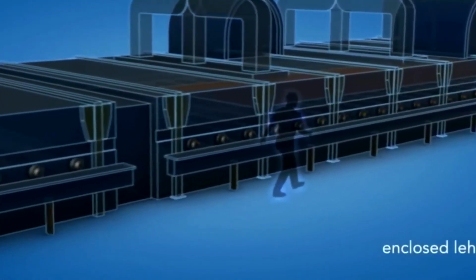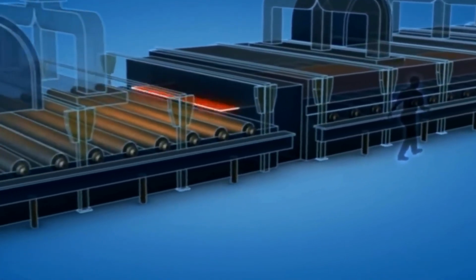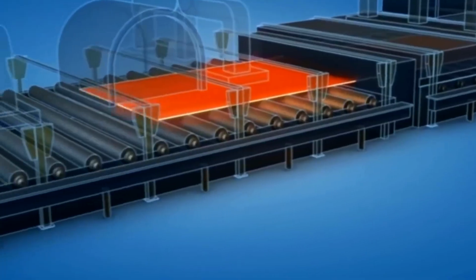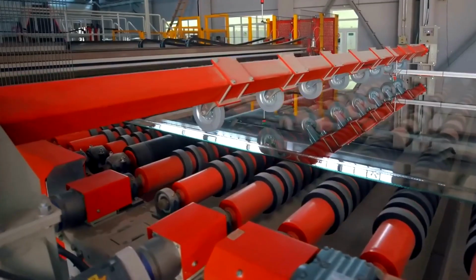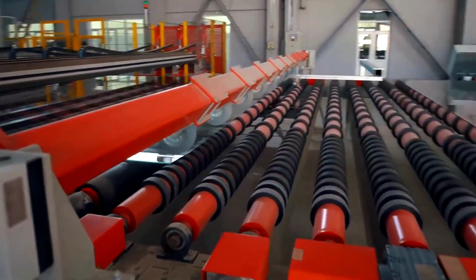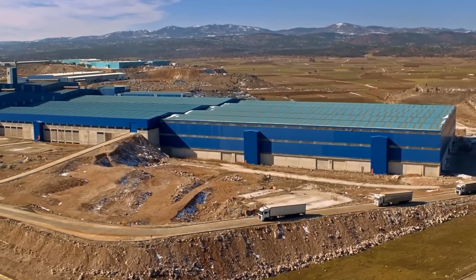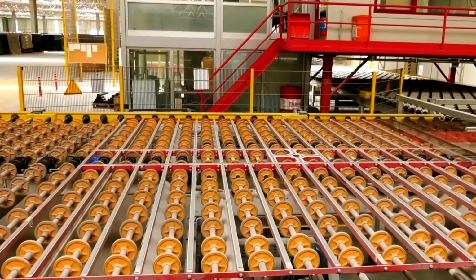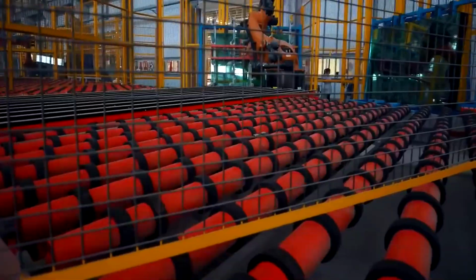From the furnace, the molten glass is not shaped by blowing, but through a specialized technique known as the float method. A continuous stream is gently poured onto the surface of a vast molten tin bath. Because of the difference in density, the liquid glass floats and spreads naturally, leveling itself into a perfectly flat sheet with incredibly smooth parallel surfaces. As the glass ribbon flows forward, it enters zones with carefully controlled temperatures. This allows it to cool evenly without warping, preserving its flawless shape and crystal clear appearance.